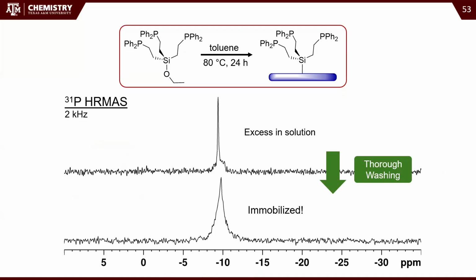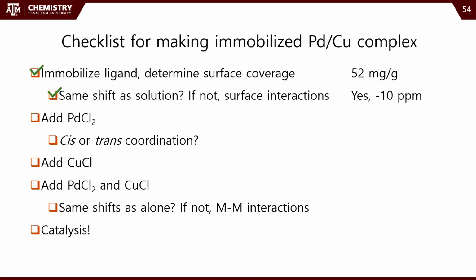It's like 10 hertz wide in a solid state spectrometer. And then as you wash the material, that sharp peak goes away, and you're just left with that broad peak underneath, which is your real immobilized material. So HRMAS can show us that everything's actually immobilized. We don't have any surface cleavage. We have the same shift about as in solution, so that's nice to know. We don't have any big, strong surface interactions or decomposition.